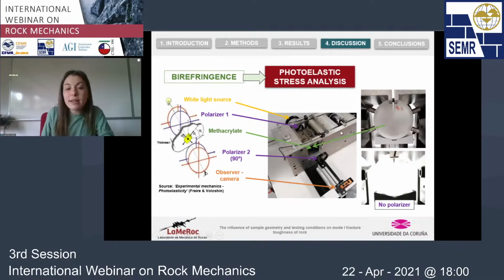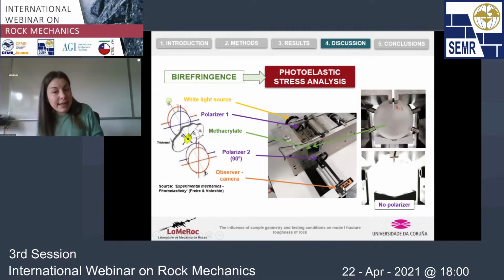This is the experimental device designed for the PCT. And here, these are the steel jaws. We placed the sample here as usual. And what we did was use a source of white light on one end, and we placed a camera on the other end. And on each side of the sample, we placed a couple of polarizers. So this is the sample before testing. This is how the sample looks when we don't use a polarizer, when we just use the white light behind. But what happens when we use the polarizer?